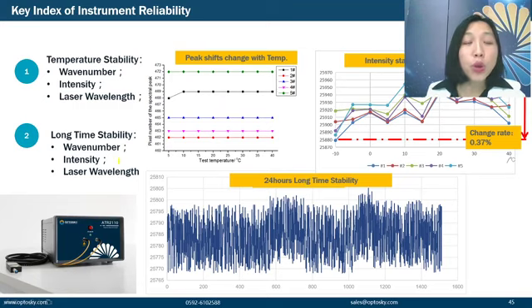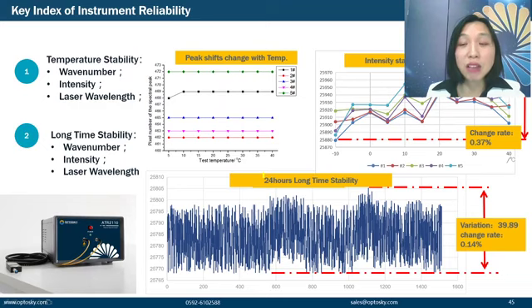And also, we performed a 24-hour runtime stability test, and our variance is only 39.89. The change rate is only 0.14%. So, after all these tests, we can say the Optosky Raman spectral instrument is very reliable.